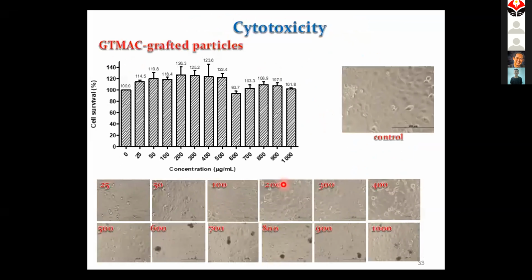Now, when they show antimicrobial properties, if you want to use them for biomedical or food contact applications, we also need to consider cytotoxicity of the materials. So we measure cytotoxicity, and if you look at cell survival on the material up to 1,000 micrograms per milliliter, it's comparable at 100%, meaning this material is not toxic to the cell. However, they still show antimicrobial or antibacterial properties, so they can be safely used in biomedical applications.